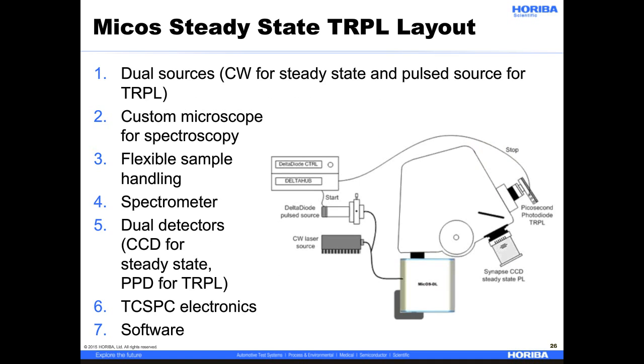The following schematic shows the general layout of the MICOS system used in the results to follow. Two sources are employed, a CW laser for steady-state PL and a pulse source for TRPL. The sources are coupled via fiber to the microscope head, which is directly coupled to the spectrometer. Two detectors are mounted at the exit, a CCD for steady-state measurements and a picosecond photodiode for TRPL measurements. A Delta Hub timing module accepts a start pulse from the Delta Diode source and a stop pulse from the PPD detector. All hardware was controlled through a PC, and software for both steady-state and time-resolved PL was used to analyze the results.